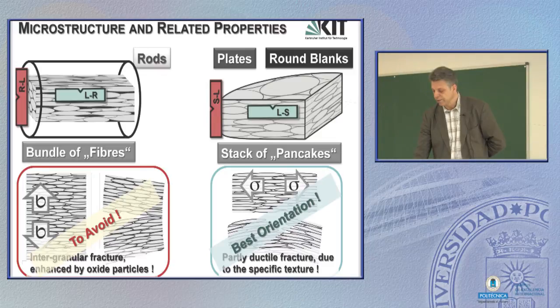So we have intergranular fracture, and depending on the oxides, which might also be mixed into the material, this behavior might even be enhanced. In some other cases, the opposite. And of course, the same is true for plates or round blanks. If you load the pancakes in this way, you have easy fracture.